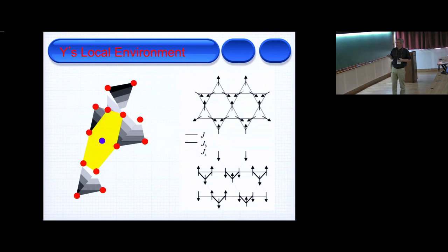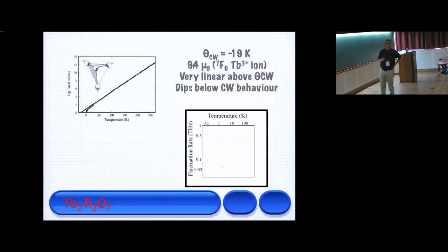And so how we've put all that together is actually that I can't do it on a corner sharing tetrahedron. My drawing abilities are useless. But on a triangular system, where if you just take the planes, we're changing these bond lengths, obviously different lengths, and it averages to 0, but then you get different J's amongst all of these. You have some long bonds, some shorter bonds, and the yttrium NMR is probing some sort of average, and you're getting this discrete stuff. The muons are also seeing these very confusing local fields. Neutrons at the diffraction level are seeing this long-range ordered structure. But we believe we've been able to understand all that.